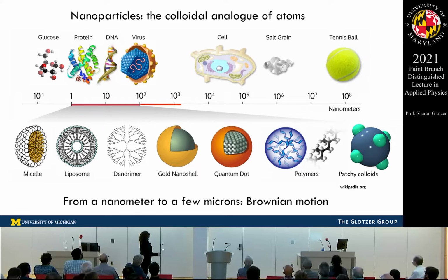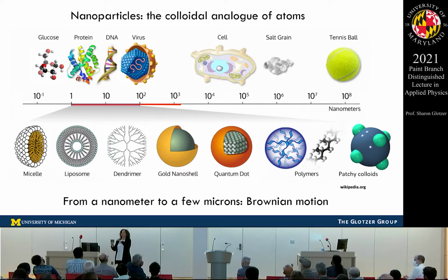As long as we're in this range of a nanometer to a couple thousand nanometers, then nanoparticles in a solution, that could be water or some organic solution like toluene, whatever's appropriate for that particular particle, the particles will exhibit Brownian motion. And if they can exhibit Brownian motion, that means that, in principle, the system can access all the different possible microstates of the system, all of the different possible ways that the particles can organize themselves and orient themselves relative to one another.